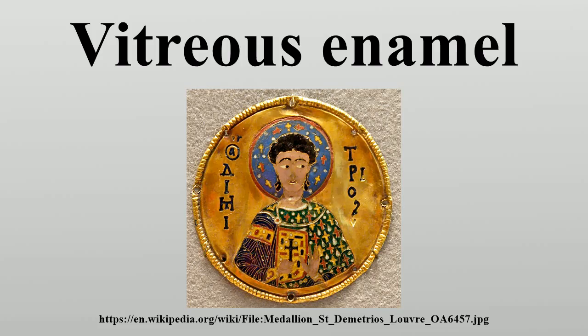The key ingredient of vitreous enamel is a highly friable form of glass called frit. Frit is typically an alkali borosilicate chemical with a thermal expansion and glass temperature suitable for coating steel. Raw materials are smelted together between 2100 and 2650 degrees Fahrenheit into a liquid glass that is directed out of the furnace and thermal shocked with either water or steel rollers into frit. Color in enamel is obtained by the addition of various minerals, often metal oxides: cobalt, praseodymium, iron, or neodymium. The latter creates delicate shades ranging from pure violet through wine red and warm gray. Enamel can be transparent, opaque or opalescent, which is a variety that gains a milky opacity with longer firing. Different enamel colors cannot be mixed to make a new color, in the manner of paint.